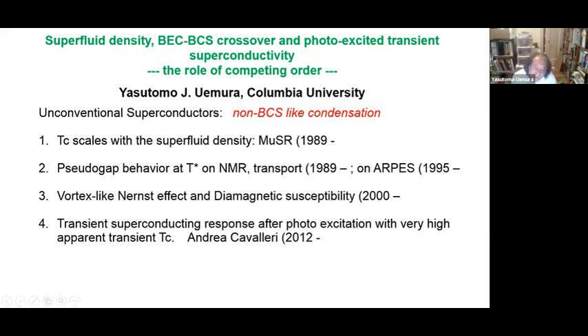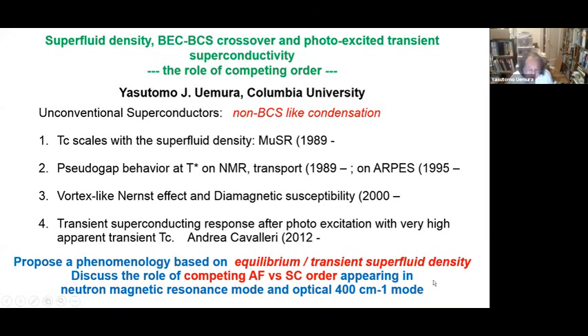with very high apparent transient Tc. So I wish to connect all these phenomena and, if possible, propose a phenomenology based on equilibrium and transient superfluid density and discuss the role of competing antiferromagnetic versus superconducting orders. And that is also appearing in the neutron magnetic resonance mode and the optical Higgs-like amplitude mode.